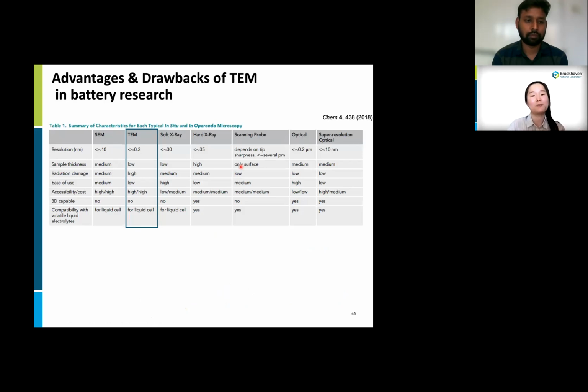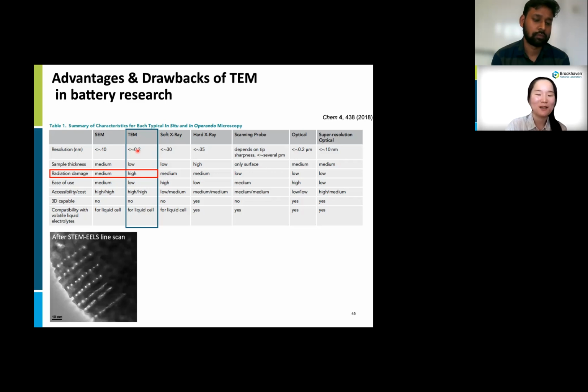Transmission electron microscope provides a wonderful spatial resolution compared to other tools, but the thing I really want to highlight is we need to be very careful with radiation damage from the electron microscope. Especially, battery materials are fragile under the beam and can be easily damaged. For example, I have a funny image from NCA particles after a STEM EELS line scan. You can see these continuous holes were formed by the probe beam.